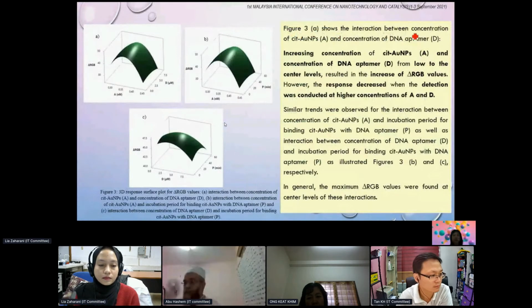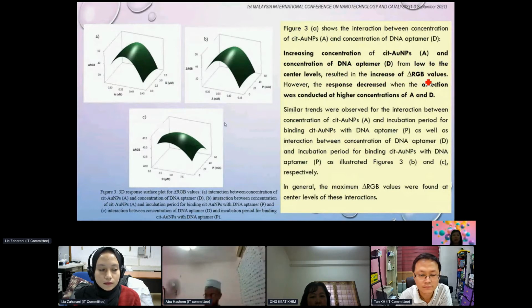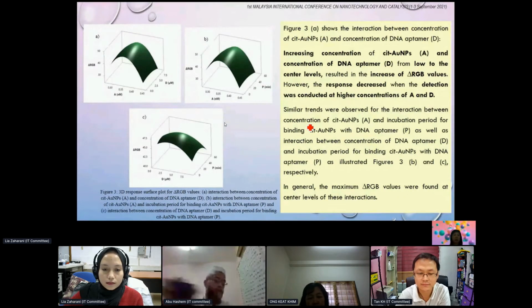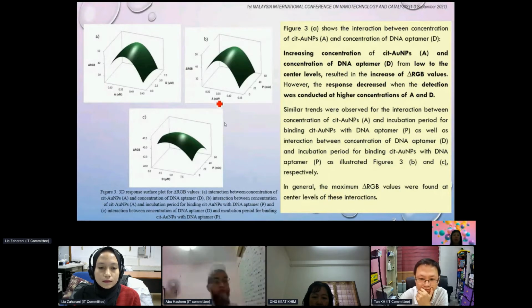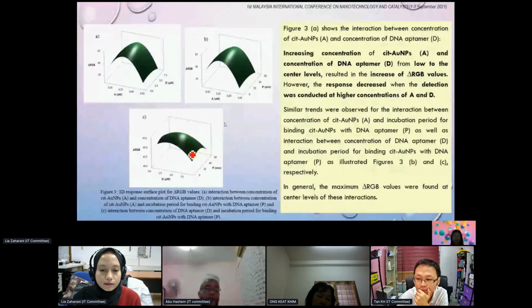Figure 3a shows the interaction between concentration of cit-AuNPs and concentration of DNA aptamer. Increasing concentration of cit-AuNPs and concentration of DNA aptamer from low to center level resulted in the increase of delta RGB value. However, the response decreased when the detection was conducted at a higher concentration of A and D. Similar trends were observed for interaction between concentration of cit-AuNPs and incubation period, as well as interaction between concentration of DNA aptamer and incubation period, as shown in figures 3a, 3b, and 3c respectively. In general, you can see that the maximum delta RGB was found at the center level of this interaction.